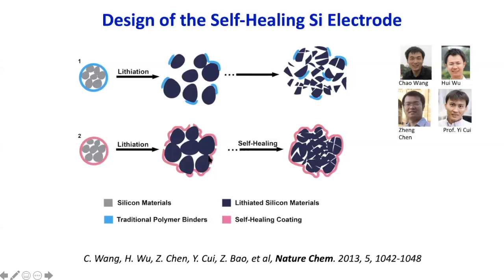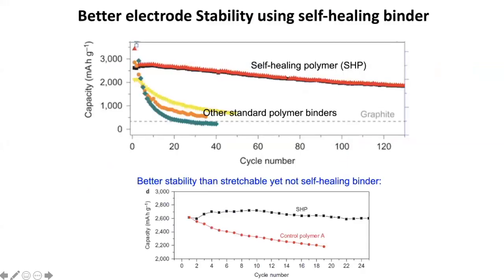So since we have been developing all these self-healing polymers in the group, why don't we apply these to the lithium ion battery for silicon particles? So we tried it, and the result was quite amazing. If we use the standard polymer binders that people have been using, if you know some polymer names, these are PVDF polymer.